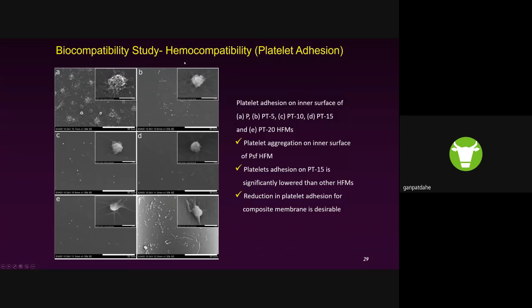Similarly, we also took blood and separated the red blood cells and the plasma. The plasma basically consists of the protein and the platelets. So we took this plasma platelet solution and incubated those platelets on the hollow fiber. This is a pure polysulfone fiber. Here you can see a cluster of platelet formation, and basically this indicates some sort of coagulation initiation. But compared to the other TPGS fibers, there's still some platelet adsorption, but not that much compared to the native polysulfone membrane.